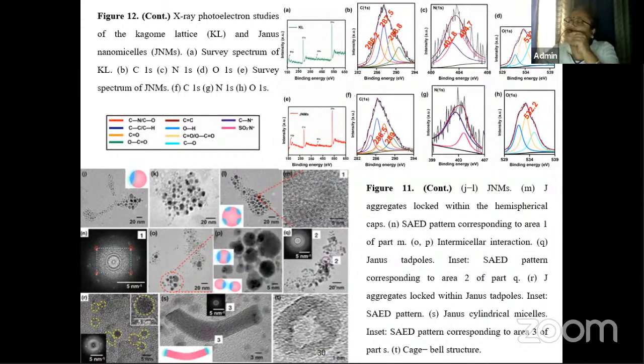There have been concerted efforts towards achieving nanostructures with sub 10 nanometer features, yet there is a relative lack of direction, stemming from structural multiplicity, lack of control, and complex low symmetry topologies which demand knowledge of target blueprints. So judicious fabrication of exotic nanostructures from block copolymers is a game of mix and weigh, often blighting bulk properties such as processability, swellability, release kinetics, impeding conformational flexibility. The materials fabricated with precise control of anisotropy, orientation, topology, molecular functionality, hierarchical self-assembly are still in their infancy in polymeric materials, where a versatile toolbox is indispensable to sail through these impediments.